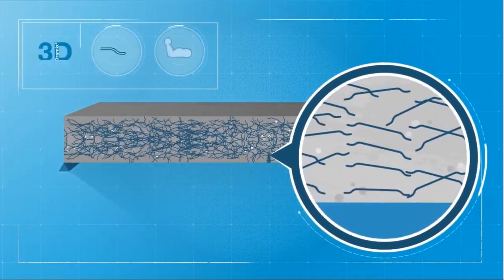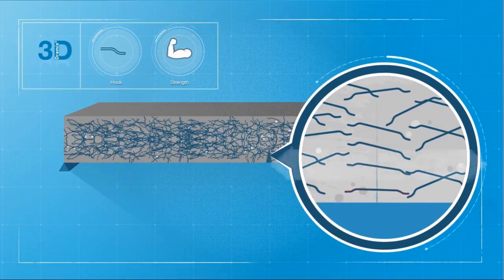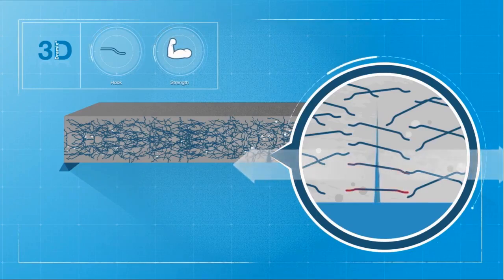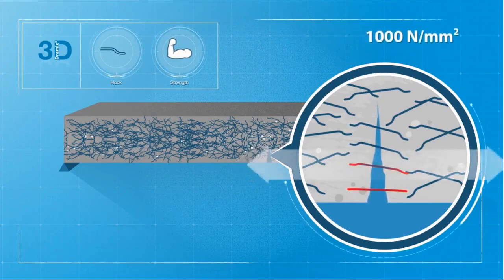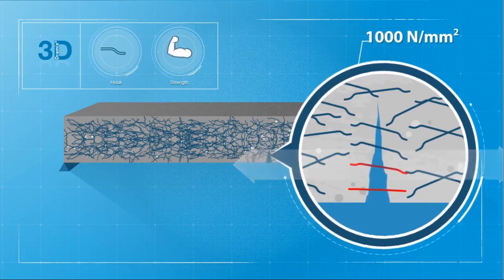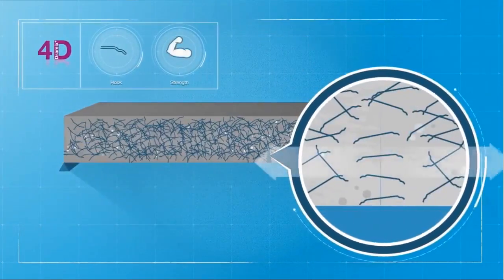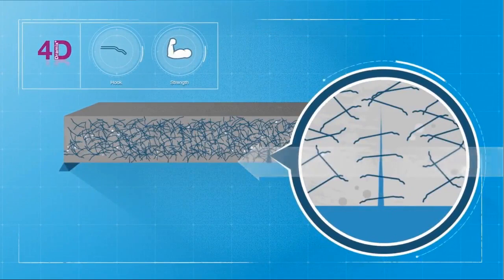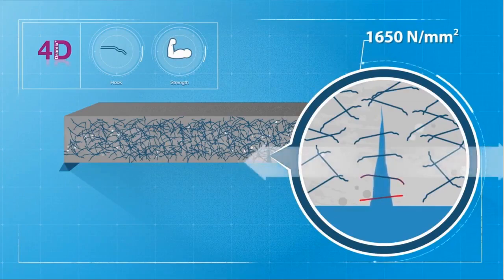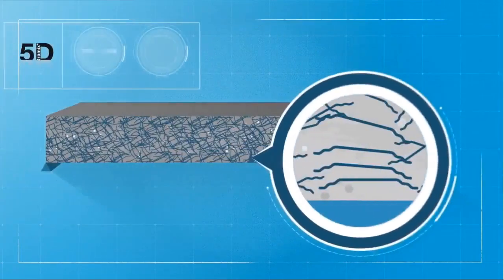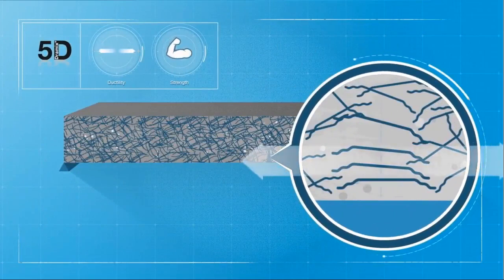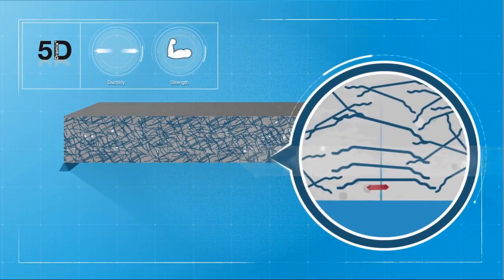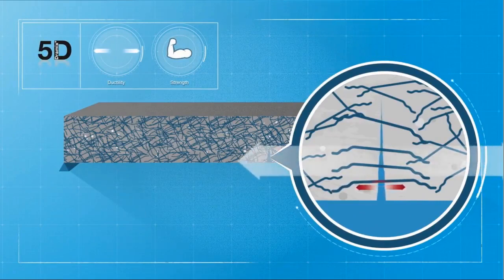First up is Dramix 3D. When a small crack occurs, the 3D hooks firmly anchor inside the concrete matrix. As the stress increases, the hook slowly deforms. As soon as the fiber loses its bond with the concrete, the pull-out takes full effect. Dramix 4D provides the same process, but with even better anchorage and a significantly higher tensile strength of 1,650 Newton per square millimeter or more. Dramix 5D behaves differently altogether. Here, the hooks never pull out from the concrete. As the stress increases, the wire slowly elongates until it reaches its maximum strength.